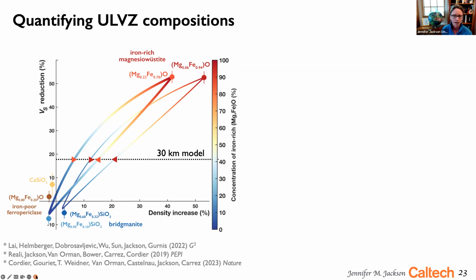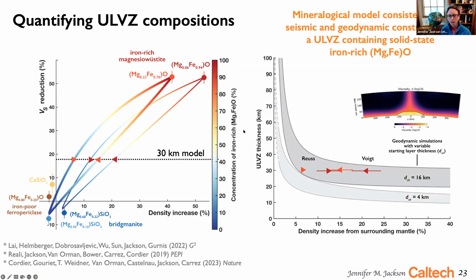And so we collaborated with geodynamicists and rheologists to constrain the viscosity and also the heights of expected assemblages that could bear this iron-rich magnesium oxide. And we see that they do indeed fall within a reasonable bound for structures that could rise up to about 30 kilometers. These values here are just the initial starting thickness of a geodynamic model that incorporates this chemically distinct structure.